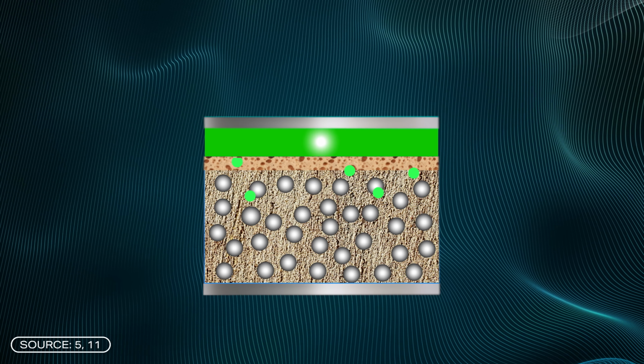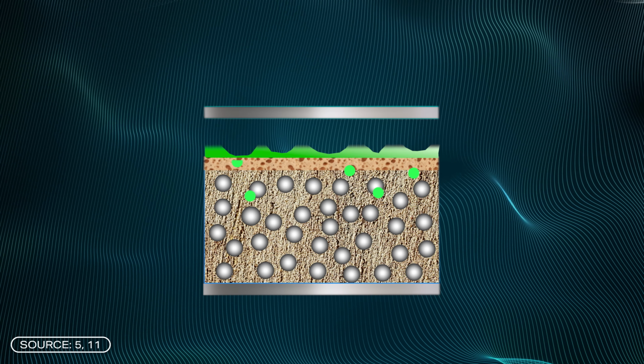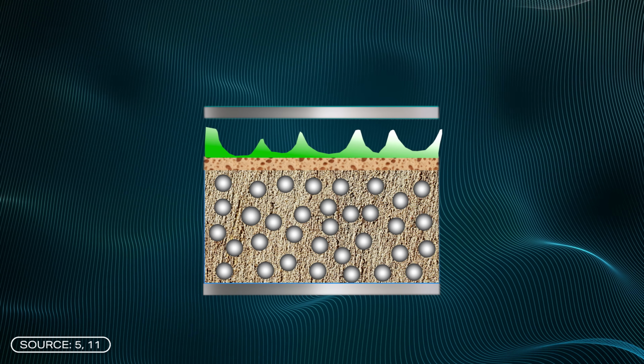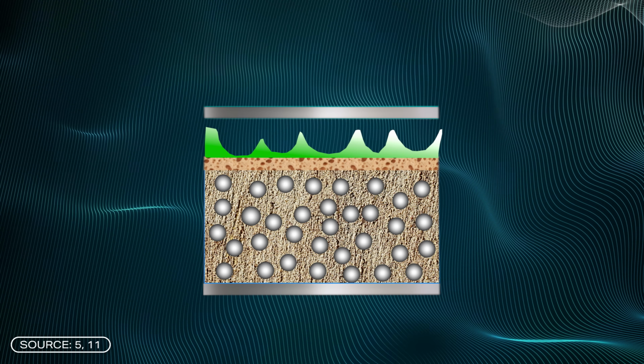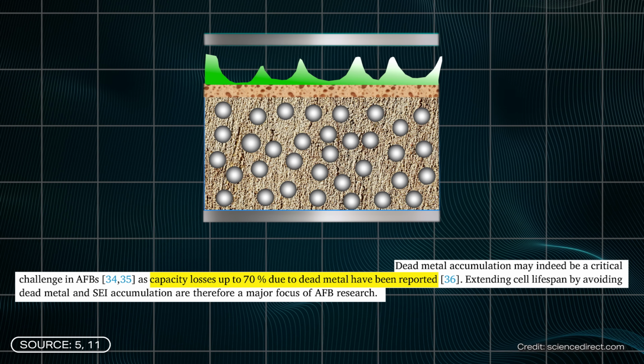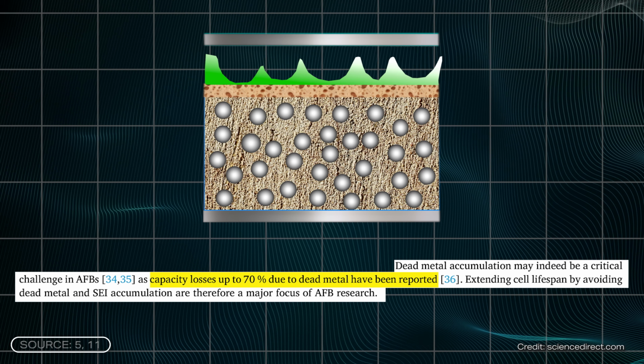So one major point is, during the first charging cycle of anode-free batteries, lithium deposits on the current collector. However, this does not result in a uniform lithium layer, but rather, depending on the circumstances, a highly uneven layer. On the one hand, this creates dead lithium, so electrochemically inactive and by that ineffective lithium. And in anode-free batteries, this loss cannot be compensated for because there's simply no excess lithium in the cell. As a result, the battery loses a significant amount of capacity, with some studies reporting losses of up to 70%.